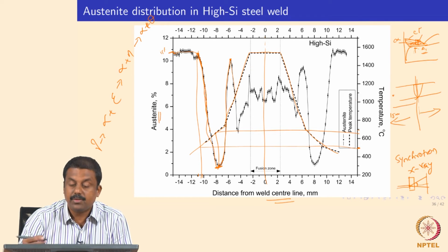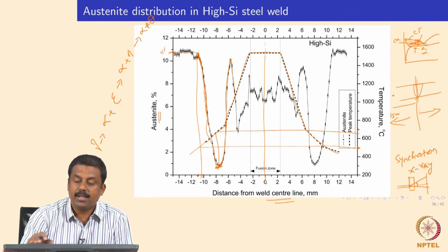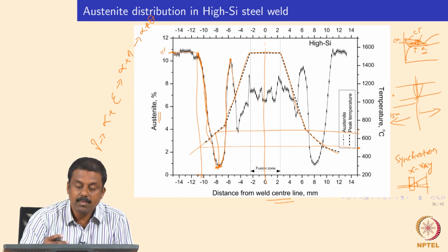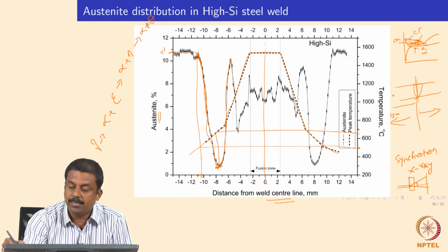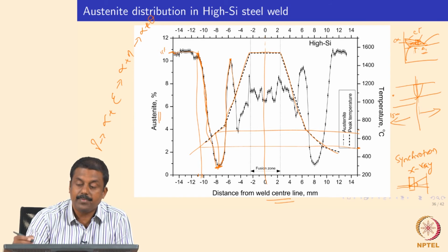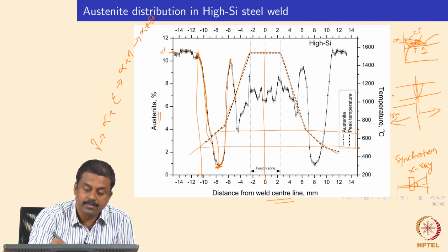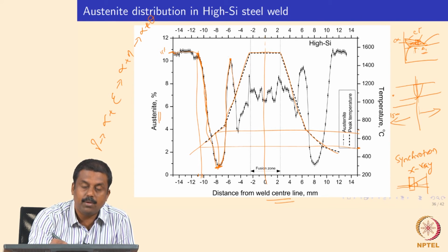So you should also be careful here. We are not welding in equilibrium condition, right. We are heating up in an extremely rapid case, so the entire phase diagram would shift upward. So you would form austenite at an A1 temperature of, say, 800 degrees centigrade in the conventional case. In this case it may be different because it is not an equilibrium case, but the principles, the fundamentals, are the same. Okay, so at this temperature, at this location, you reach the ideal volume fraction of both ferrite and